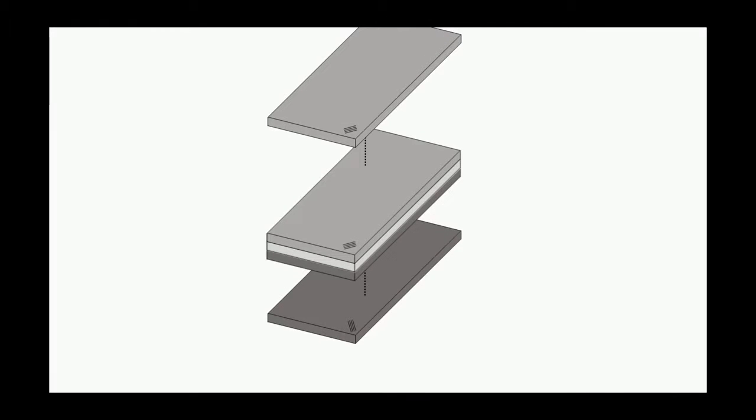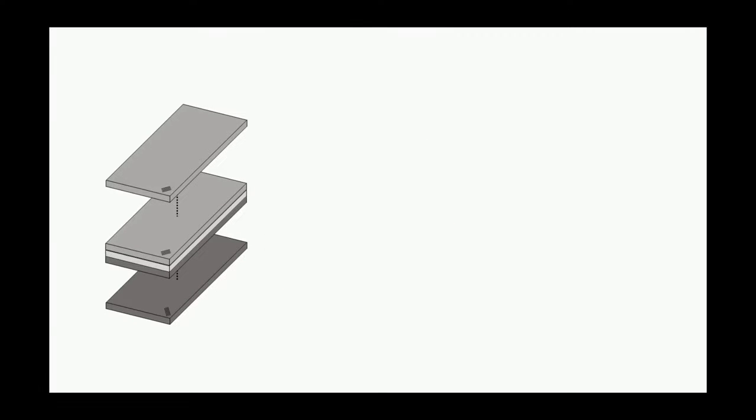The result is that we get a composite laminate where there is a reinforcement unit at each interface that we wish to reinforce. Because of the fiber orientations that we have chosen, the mismatch in fiber orientation angle always happens at the midplane of a reinforcement unit, because the upper layer of the reinforcement unit will match the fiber orientation of the layer above, and the lower layer will match that of the ply below.